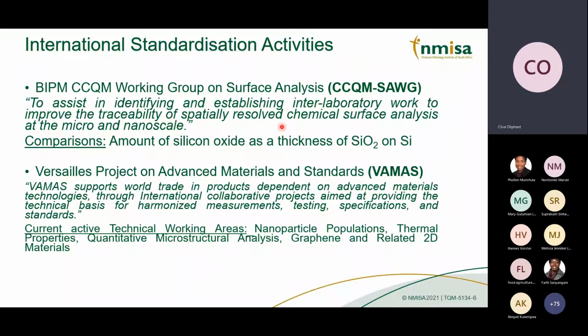This is just to assist in identifying and establishing inter-laboratory work to improve the traceability to the SI units of spatially resolved chemical surface analysis at the micro and nanoscale. For example, the amount of silicon oxide as a thickness of SiO2 on silicon. This was important for the new kilogram project, which I showed in a previous slide on the silicon sphere.